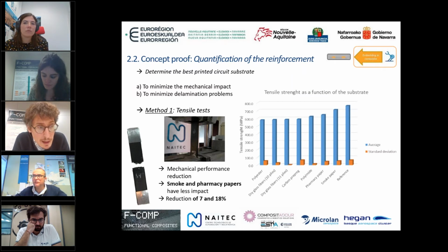In here, we saw that the most promising were the papers with different grams, and even with them, we have a reduction of between 7 to 18%. Even with the polyamide, we have this 18%. In any case, below 20% reduction of the properties of the full part.